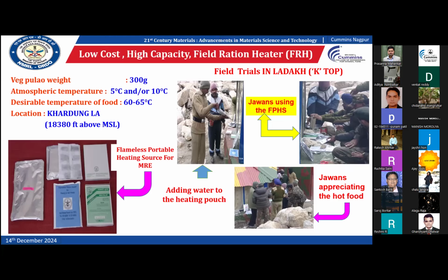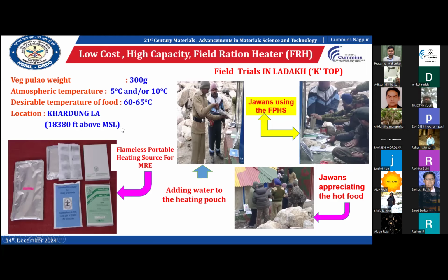After adding the water on both sides, 50 ml on one side, 50 ml on the other, you see the soldiers are doing the job. And within 15 minutes, they got more than 85 to 90 temperature. And this trial we successfully carried out 18380 feet above MSL, at Khardung La. It is very close to the China border.